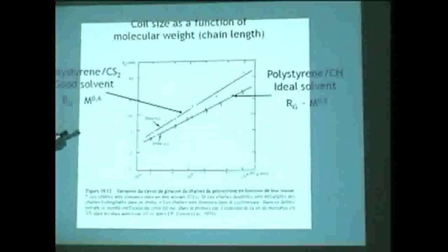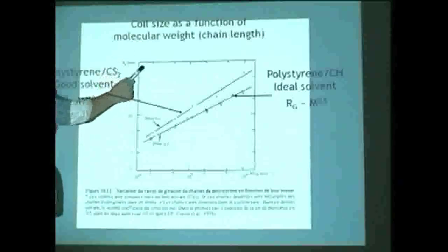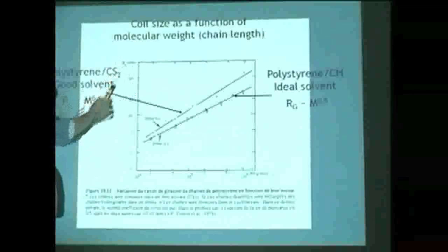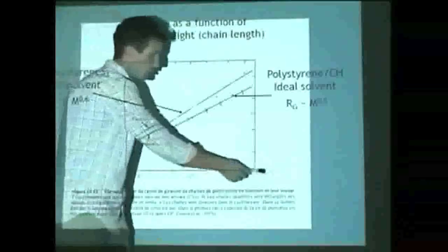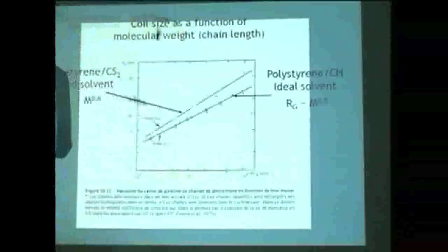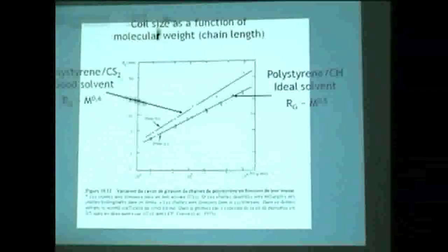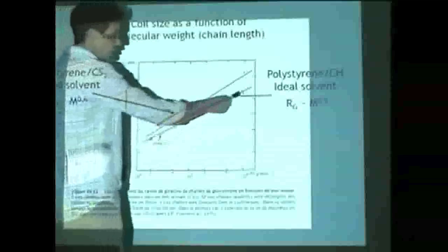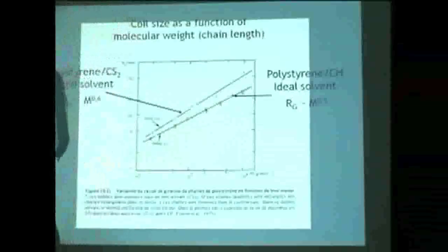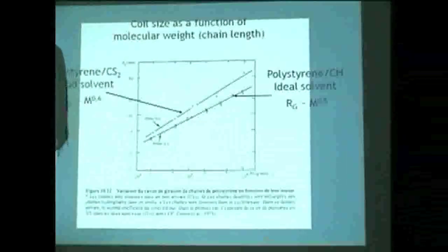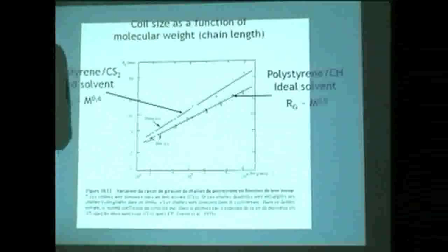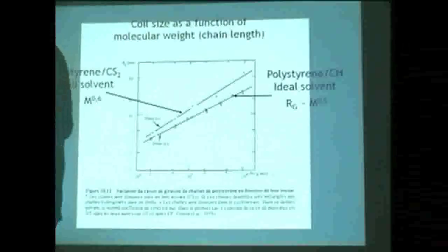And if you measure, this is what has been done here, here is plotted the value of the gyration radius as a function of the molecular weight of the chain. So it means as a function of the length of the chain. And here you see that the gyration radius varies as the square root of the molecular weight. Okay? So I write here on the...